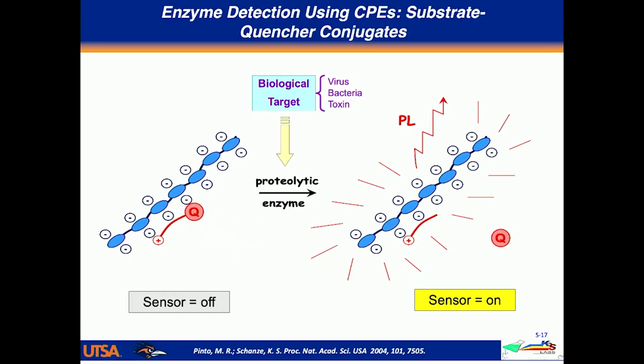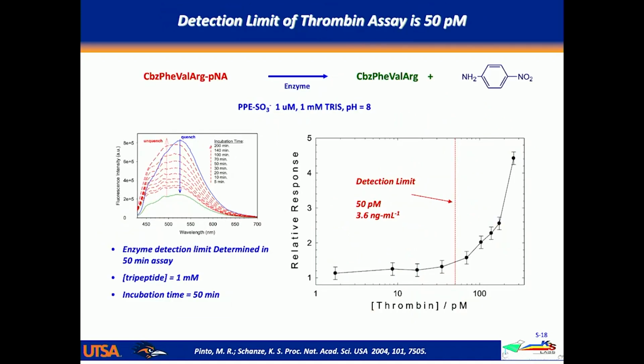So it's an enhanced signaling system where the polymer is just acting as a transducer. It's measuring the presence of the quencher in the system. So we developed that, and one of the things that we did was look at the detection limit of this system. The one that I'm showing here is where we used a tripeptide. It was labeled with a para-nitroanilide as a quencher group, so para-nitroaniline is a good electron acceptor. So that's taking the place of what I've used viologen for previously.